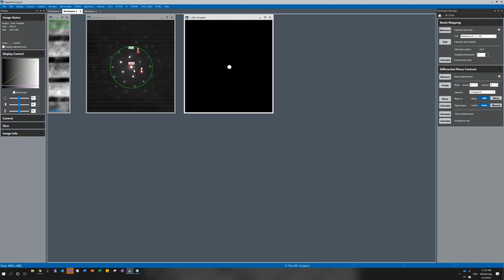The way you measure this is when you are in the diffraction image, you defocus the beam and you get a shadow image of your sample. From that shadow image compared to your STEM image, you can measure how much rotation you have. Okay, I have everything set up now. I'm ready to calculate my strain map.